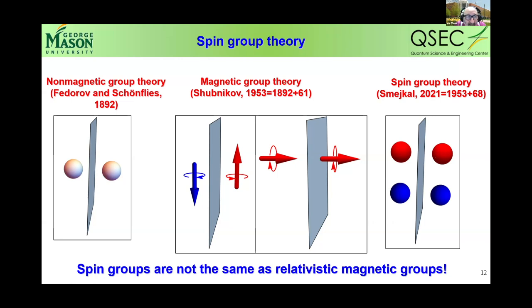So we cannot live with non-magnetic group theory if we want to classify altermagnets, but magnetic group theory is just too much. It introduces unnecessary distinctions, which I will show on the next slide, between things that from the altermagnetism point of view should be considered essentially the same. So for that reason, Libor Smejkal, and many people did similar things before, the idea is that you should be specifically non-relativistic. And why am I saying non-relativistic? Because the only way spin direction can manifest itself in crystallography is through spin-orbit coupling. Otherwise, spin space and real space are not coupled. So it might be interesting to introduce a system which consists of two-color objects, which we can call spin up and spin down, but the direction doesn't matter. I like the version that Libor developed, incidentally also nearly 60 years after Shubnikov, which is very well tailored for classifying altermagnets.